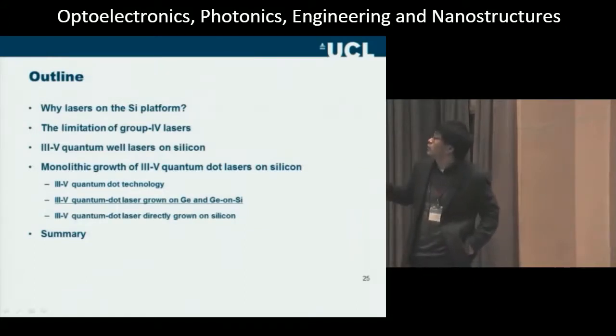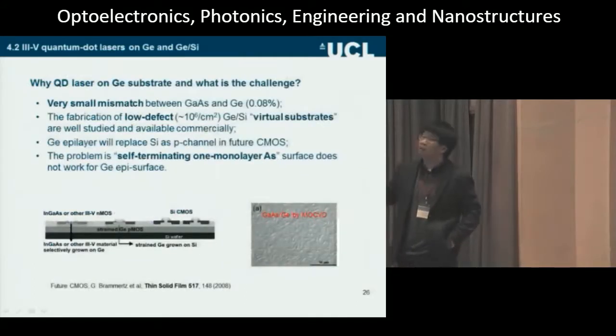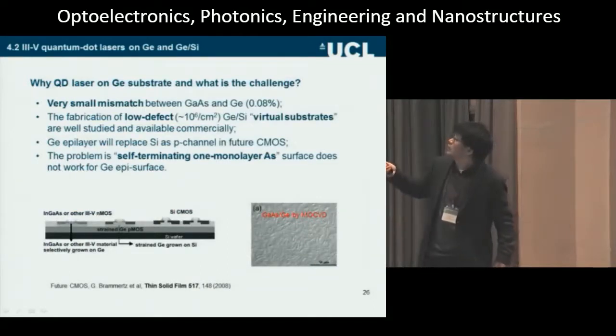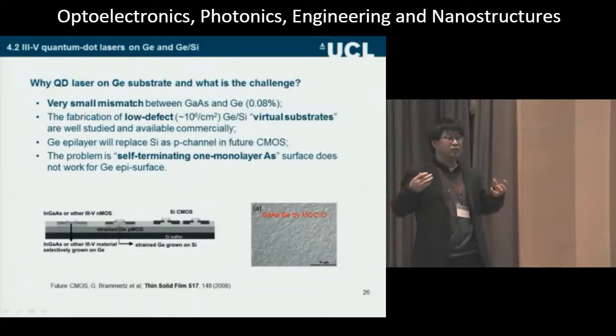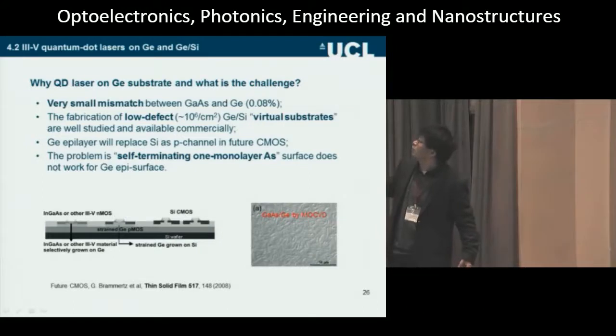So the first thing we try is grow quantum dots on germanium. The reason is germanium and gallium arsenide have a very small mismatch, and also the virtual substrate is available with very low defect density. Nowadays germanium is used in your CMOS, called strained CMOS. But the problem is the self-terminating arsenic layer doesn't work, because arsenic at high temperature will diffuse in germanium, destroy the surface.